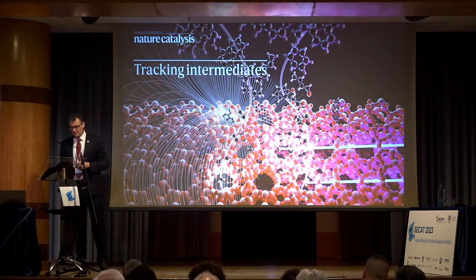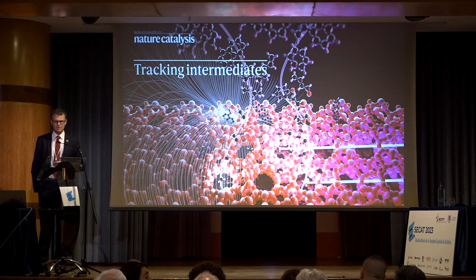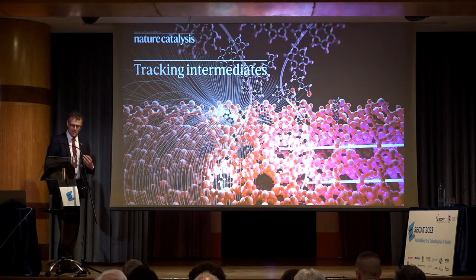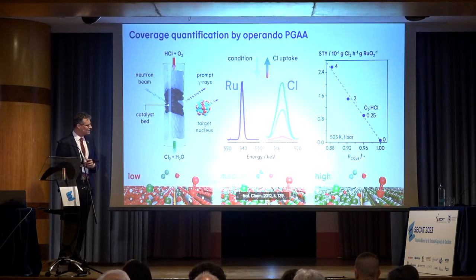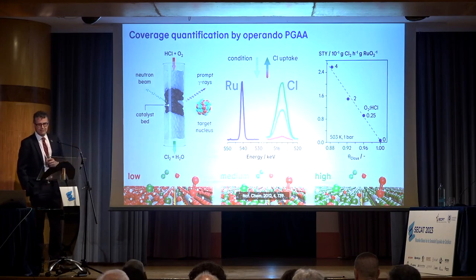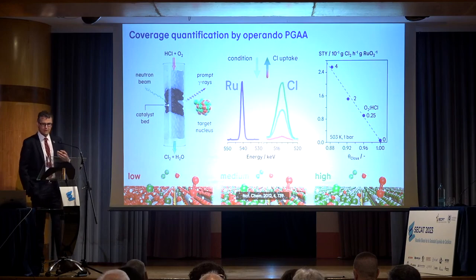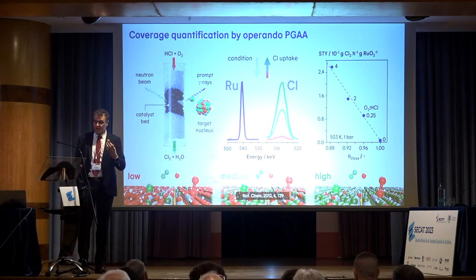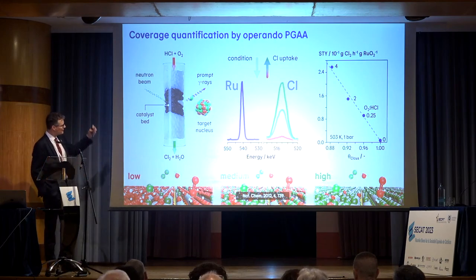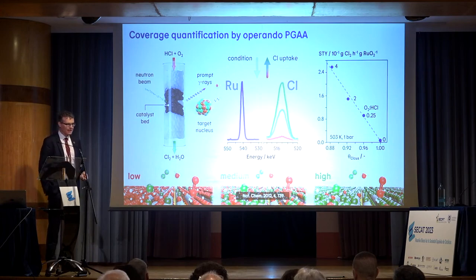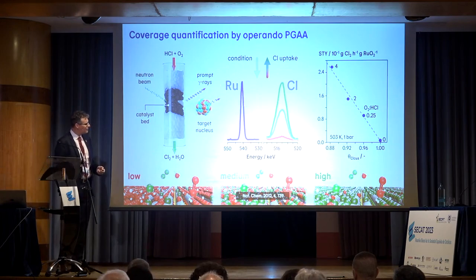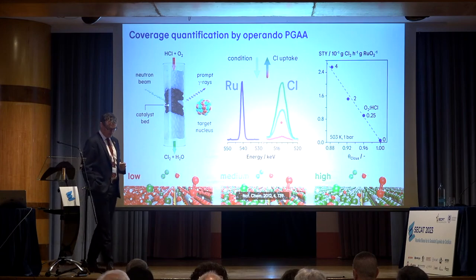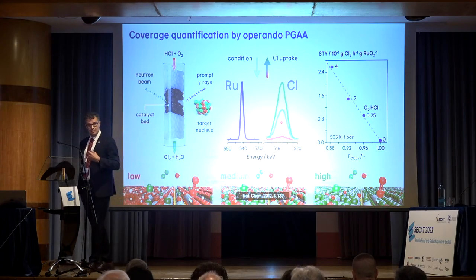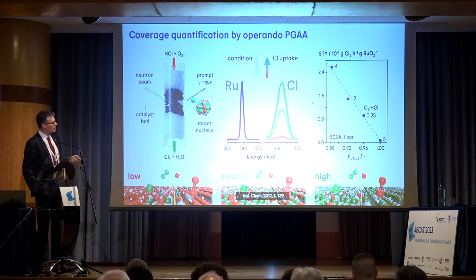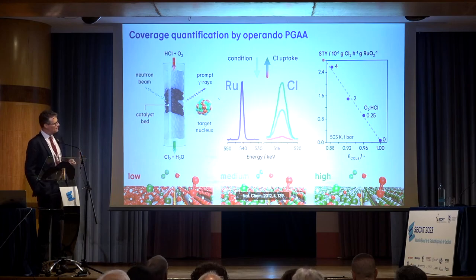My favorite one out of the many that we develop, you imagine this is halogen chemistry, so corrosion is a big issue. Handling these reactions is not very easy. My favorite one is this one, where we use prompt gamma activation analysis. That's a technique that requires the use of cold neutrons. Cold neutrons are basically bombarded over the catalytic material under working conditions. They excite all the nuclei in the catalytic reactor, and then upon decay, they form gamma rays, and the gamma rays have characteristic energies, and the intensity of these signals are proportional to the concentration. So with this technique, we could develop a correlation between activity and coverage.